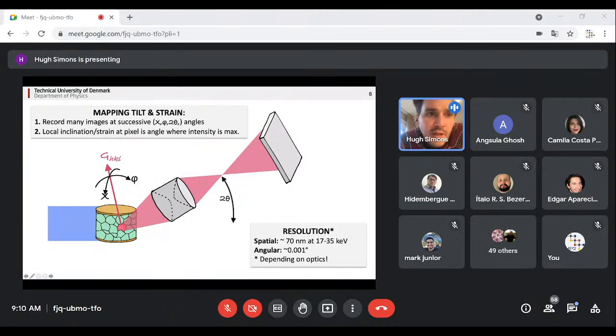So we can map, for example, tilt and strain by recording many different images while changing, for example, the sample tilt across these two orthogonal angles, or also changing the 2 theta angle of this microscope. Then when we have a stack of images at different rotations, we take the position where the intensity of any pixel is the maximum, and this corresponds to the true orientation or strain of that lattice.